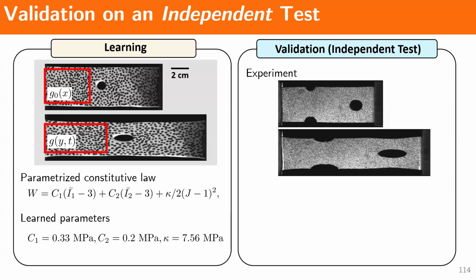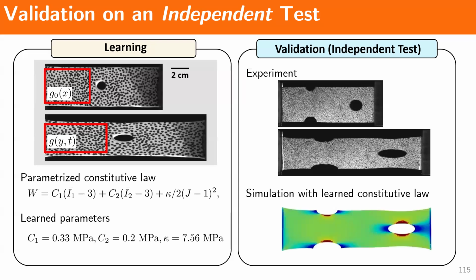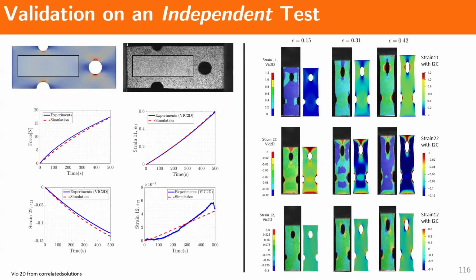So what we did here is we ran the validation on an independent test specimen with a different geometry. You can speckle it with some spray paint and then run the DIC problem. You can also run the simulation with the learned constitutive law that we've gotten from the inversion. We use Vic2D from Correlated Solutions to perform our DIC. And here's the quantitative difference between the two. The blue curve here is from Vic2D data, and the red curve here is from our algorithm. We see that quantitatively they match with each other, the strain fields as well as the force.